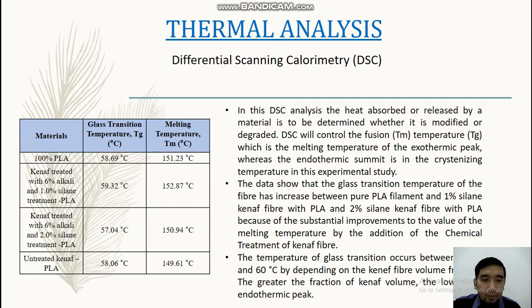So for the glass transition temperature, 100% PLA is 58.69, for 1% 59.32, 57.04, 58.06. For the melting point, 100% PLA 151.23, 152.87, and 150.94. For the untreated Kenaf 149 degrees.